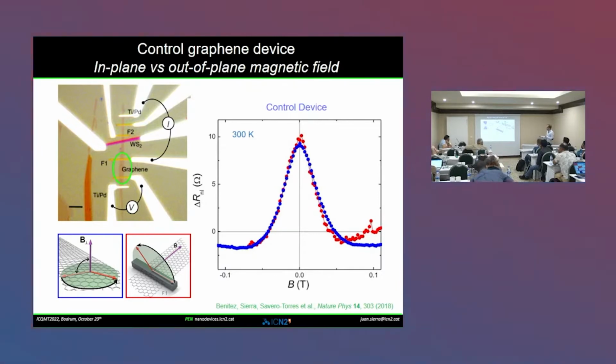So in principle, you have these two effects. You have spin polarization out of plane arising from the spin Hall effect, but you also have this spin density that is coming from the spin galvanic effect. Another question is how we detect this. Again, we use spin-sensitive contacts here, and how can we disentangle and know if the spins that we are detecting are coming from the spin Hall effect or from the spin galvanic effect? It is obviously by playing with the geometry of your magnetic field.